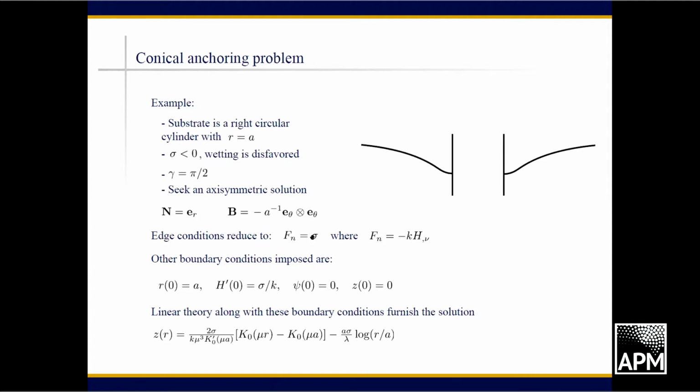And the larger the magnitude of the adhesion energy, then the larger is this transverse shear force, which has the effect of pushing the bilayer vertically downward. Also, the transverse shear force is related constitutively to the normal derivative of the mean curvature in the membrane at the boundary, and K is a bending modulus associated with a specific form of the energy.